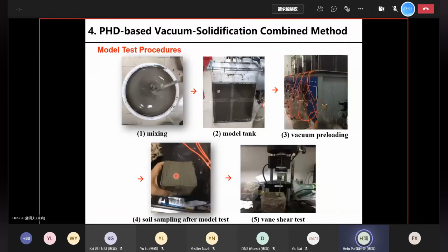This is the test procedure. So we mix the slurry, and then we place the slurry into the model tank, and then we start the vacuum pump. And after the model test, the slurry is turned into soil. So we take out the soil sample for other type of tests, such as strength testing.